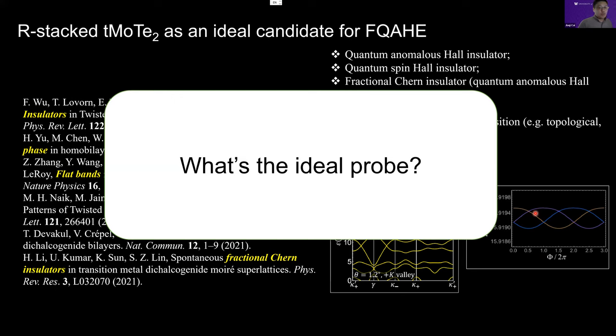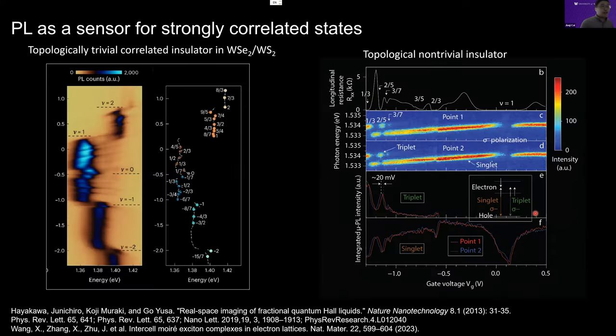The next question is, what is the ideal probe to see those topological properties of the system? In our lab, we develop lots of different probes. On the left, we show one of our results using optical spectroscopy, in detail photoemission or photoluminescence of the semiconductor. What we can see is that if you fractionally fill the Moiré superlattice and observe the photoemission, at a certain fractional filling of the Moiré superlattice, you can see the PL is sharply enhanced. That is because this is the interlayer exciton emission.